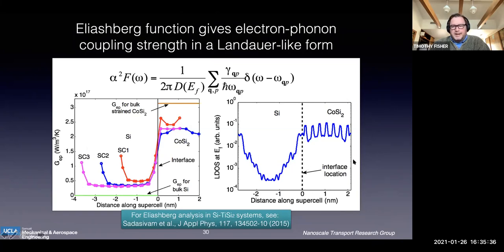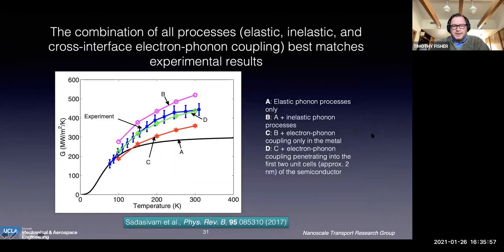We also looked at density of states at the interface and away from the interface. But ultimately, this Eliashberg function is the one that controls that coupling rate. And that's something that comes from the DFT. And we've written papers on that for titanium silicide silicon as well, that if you're interested, you should definitely read in addition to this one. All right, so this graph is the graph I'm most proud of in my career. I kind of doubt that I'll ever be more proud of a graph.